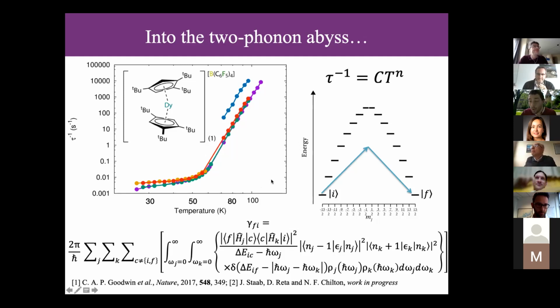And those are the acoustic and the pseudo-acoustic modes of the solid state, which are essentially pseudo-rigid translations, rotations, tiny little things. And so it's very hard, and they couple all kinds of different motions, and they project onto local modes in very non-trivial ways. And remember, if you have a crystal structure, the space group, whenever you do a phonon, you're breaking the symmetry, right? And then you have different wave vectors which describe how the phonon maps onto different neighboring unit cells, and the periodicity of the lattice, and you break the symmetry. So certain symmetries are broken by vibrations anyway, and how these map onto the pseudoacoustic spectrum is really non-trivial, but it's a really good question.